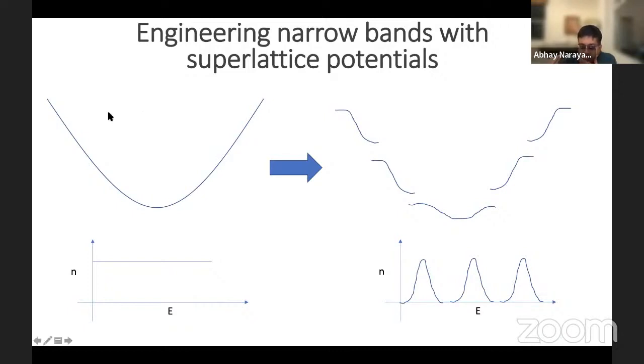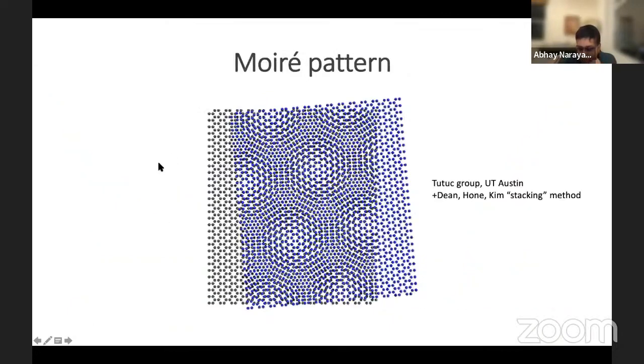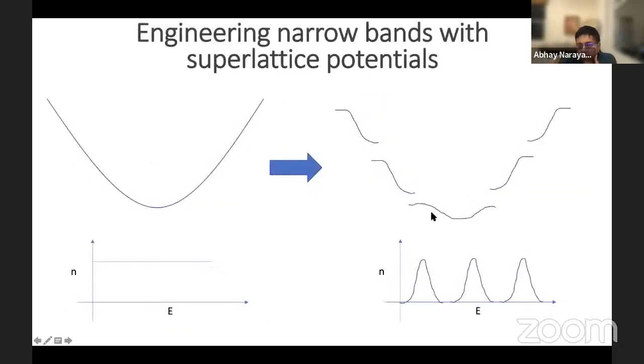So the basic idea is very simple. You take, let's say, a two-dimensional semiconductor, which in two dimensions has a constant density of states. If you apply a superlattice with some periodicity, then you will break up the conduction band of the semiconductor into a bunch of subbands. Within each of these subbands, the width of that band can be relatively narrow, which is set by the size of the superlattice potential in real space. And then the interesting physics that you are interested in happens in the lowest of these subbands.